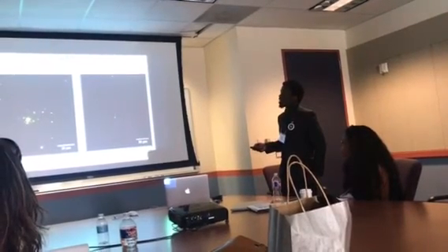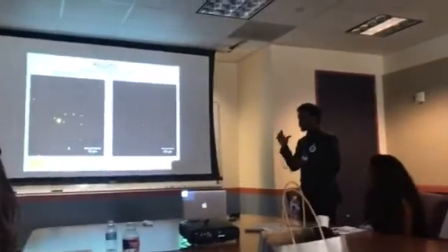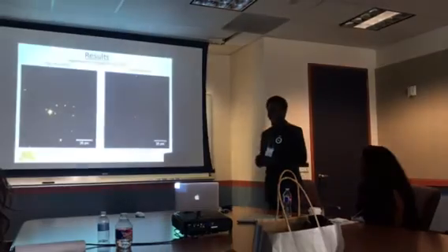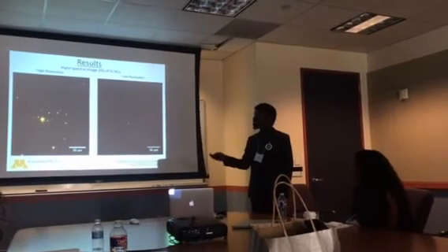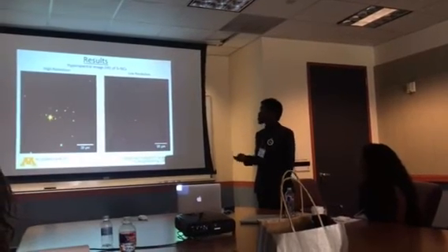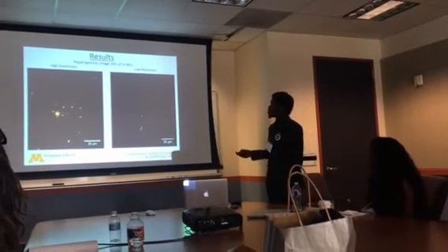Here's another characterization technique provided by my graduate mentor, Bo Z. It shows a dark field image of what is actually taking place as the aggregation due to lack of solubility. The brighter peaks basically show us that, when it's in solution, parts of the silicon nanocrystal were harder to dissolve in the water than other parts. That actually made it a little more difficult to pipette and to transfer to the 96 well plate, as you'll see now. And here's just a low resolution image of what's actually taking place.